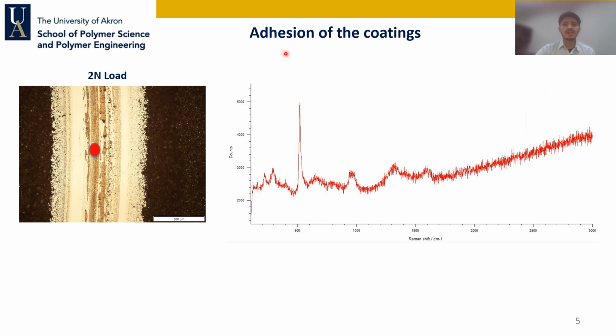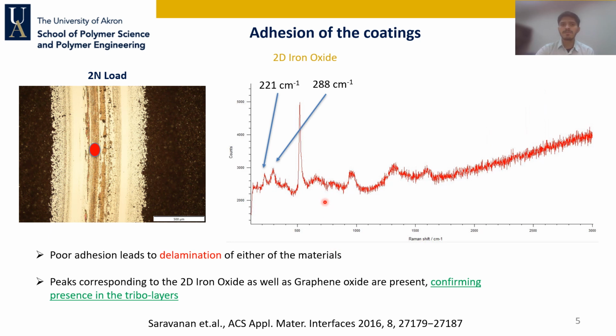Next, in order to address the adhesion problem of graphene oxide, we did the Raman spectra after the tribo-layer formation took place. What we observed was that poor adhesion leads to delamination of either of the materials, and we don't want that. So we confirmed that by doing the Raman spectra, and on the tribo-layer, given by the red dot, both the 2D iron oxide peaks as well as the graphene oxide peaks were present, confirming the presence of both the materials.